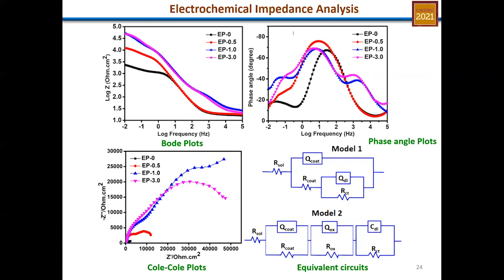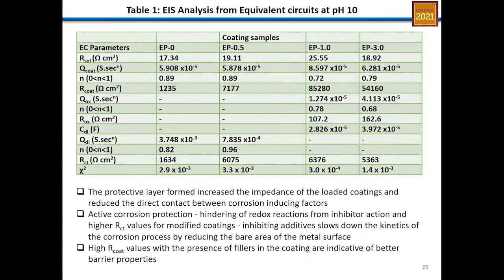And we modeled it with the ZSimpWin software, and we were able to obtain the electrochemical circuits for the analysis. So from the table of the EIS analysis, we realized that the coating resistance, which is the output, shows high values, which is indicative of better barrier properties, and the charge transfer resistance also at 1% reflects high values, which is also indicative of kinetic reactions at the electrode-electrolyte interface that resulted from the release of the active inhibiting material from the nanocomposite on the surface of the coating. So the protective layer formed increased the impedance of the loaded coatings.